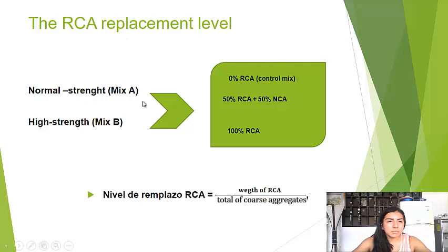In this investigation two mixes were used: mix A, normal strength, and mix B, high strength. The control has no replaced aggregate concrete, one has 50% recycled aggregate concrete plus 50% natural aggregate concrete, and the other has 100% recycled aggregate concrete. The replacement level is defined as the ratio between the weight of recycled aggregate concrete and the total of coarse aggregate.